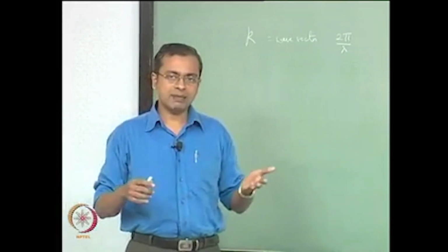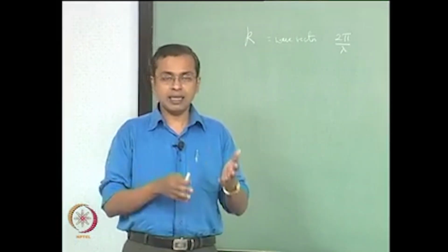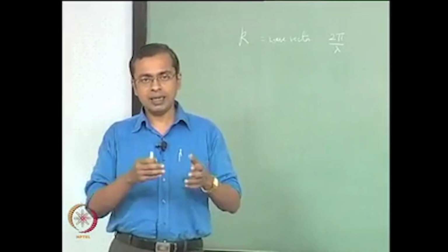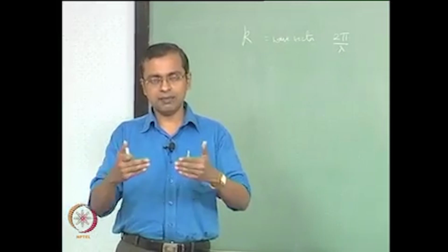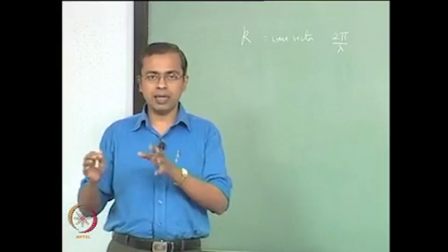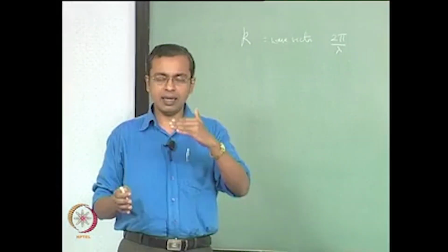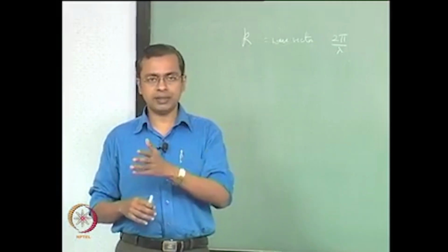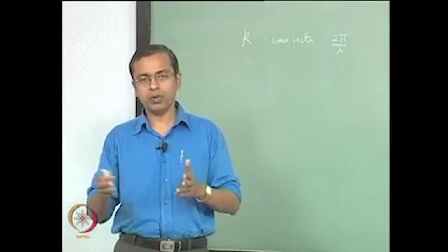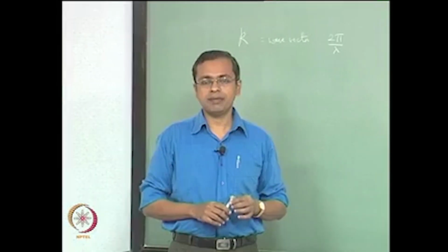Of course, last class we looked at the reciprocal lattice as an independent entity. We just basically said that, given a real lattice which has unit vectors a1, a2 and a3, we can specifically create a reciprocal lattice which corresponds to this real lattice with the definition of the reciprocal lattice vectors, unit vectors in the reciprocal space b1, b2 and b3, having specific relationships to a1, a2 and a3. So we had a cross product: b1 was a2 cross a3 divided by the volume of that unit cell, and similarly b2 and b3 were described.